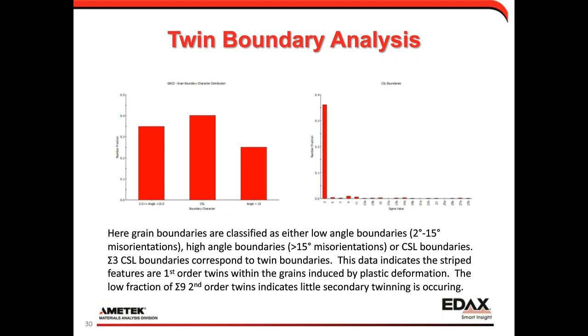So twins are boundaries with very specific misorientation geometrical relationships that can be described in what's called CSL, or coincident site lattice theory. And so primary twin boundaries are what are termed sigma-3 CSL boundaries. If you take a grain and you twin it, you'll get that CSL3 relationship. If you twin it again, you'll get 3 to the n, or in this case, 3 squared, or sigma-9 second-order twin. And so what we're able to do is to classify all the boundaries in there, is to say, are they low-angle boundaries, in this case 2 to 15 degrees, are they high-angle boundaries greater than 15, or are they CSL boundaries? And so then these are twin boundaries.